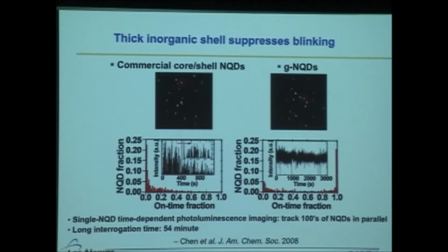And I want to also point out that on a conventional core shell system, not only are the particles turning on and off and blinking, but you can see that the intensity is declining over time. And that's an indication of photobleaching. So conventional quantum dots under continuous excitation photobleach, whereas the giant quantum dots we found are not only exhibiting the suppressed blinking behavior, but are non-photobleaching.